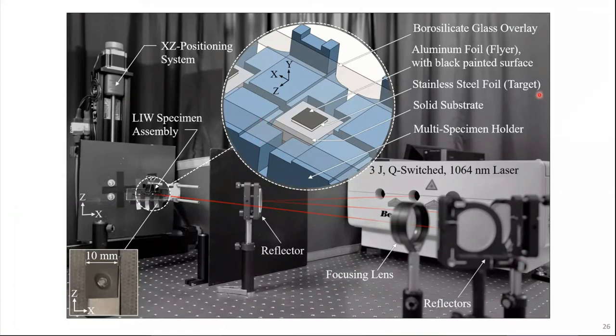To give you an idea, this is the same laser lab, but what we have over here is a difference in the setup. So this over here is our laser impact welding setup. The inset image is slightly different. Again, you see the two foils, you see the substrate on which the lower foil, the stainless steel foil, is mounted. The aluminium foil, which is attached to the transparent overlay, is painted black. And you have a laser coming in and hitting it from the negative Y orientation. And the result of that is this weld that you see over here in this inset image on the bottom left.